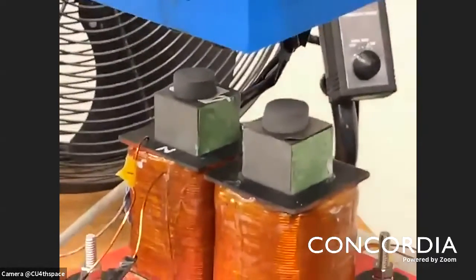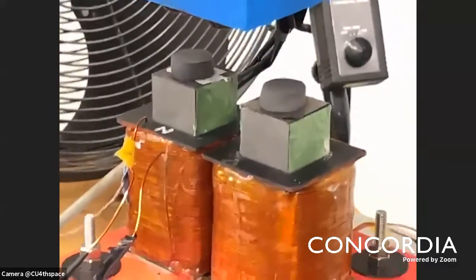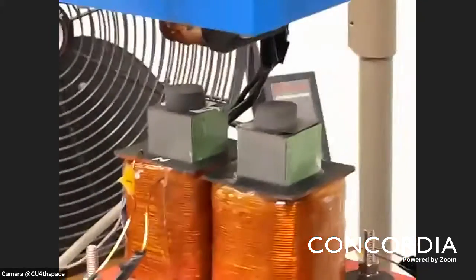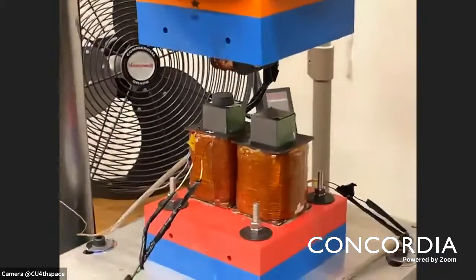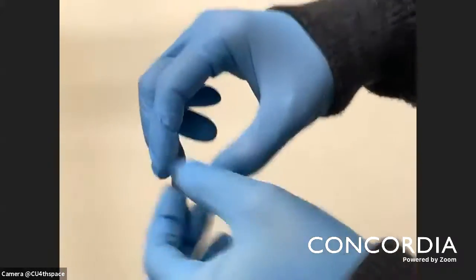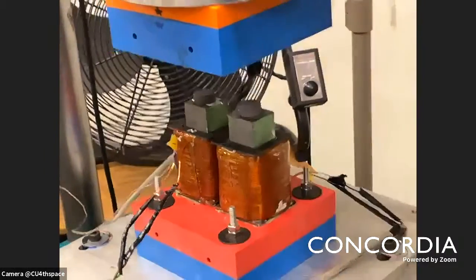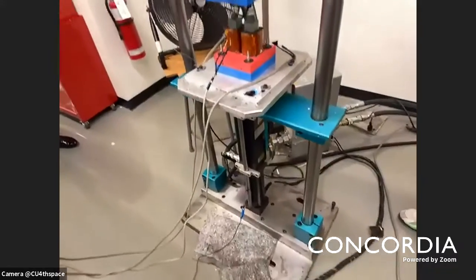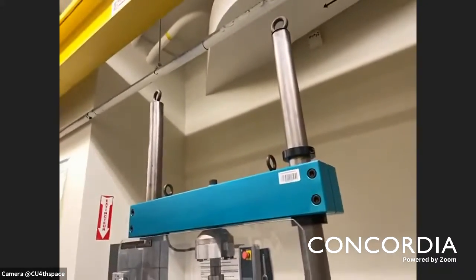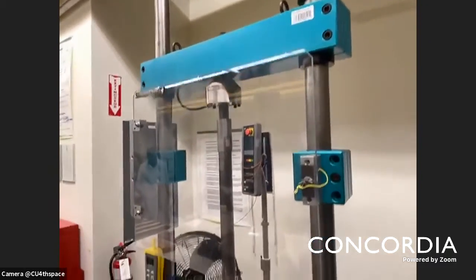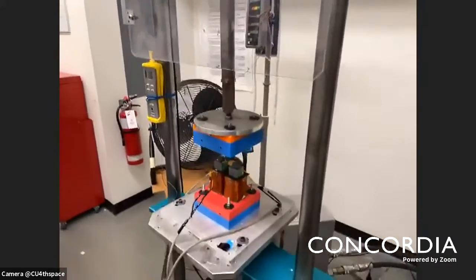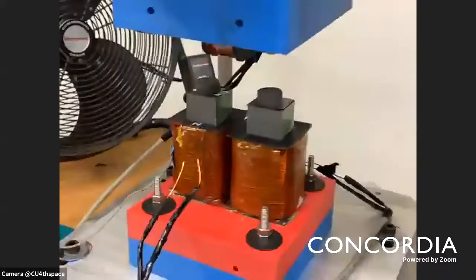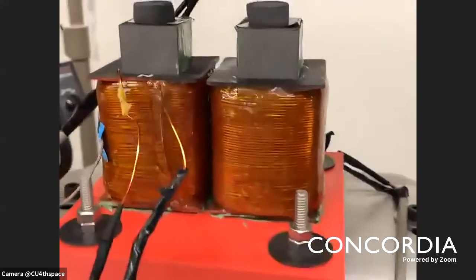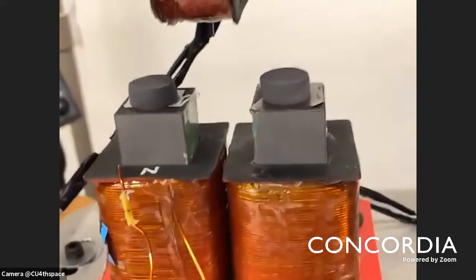As I said, there are mainly two modes of operation, shear and compression. Here, my focus was to assess the properties in the compression mode. Unlike the shear mode, it is very difficult to provide a magnetic field simultaneously parallel to the mechanical loading. A rheometer can easily create a shear deformation while providing a magnetic field perpendicular to it. It's a very easy task. However, providing field and mechanical load simultaneously is quite difficult, and we need to come up with a design that allows both in one direction.